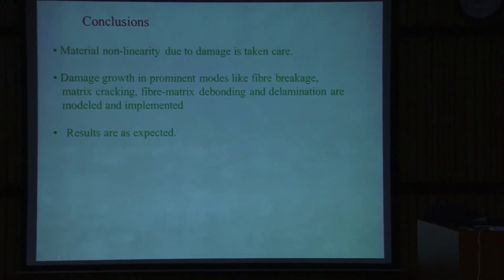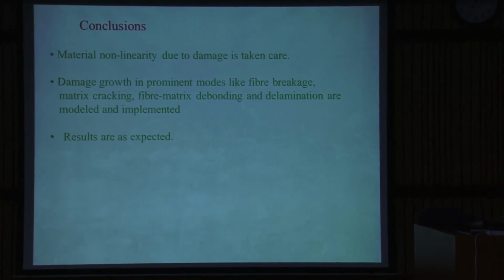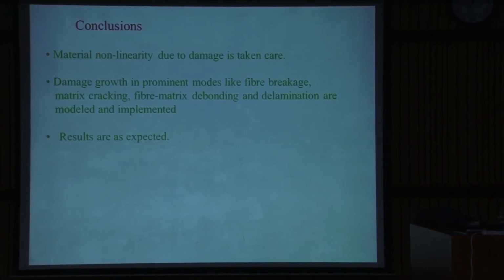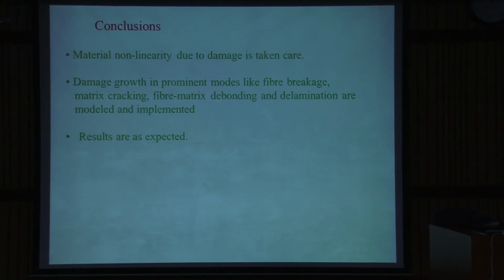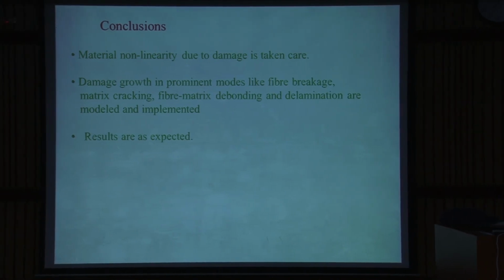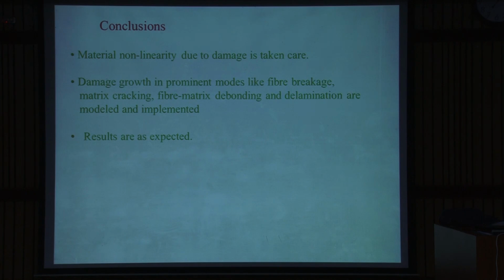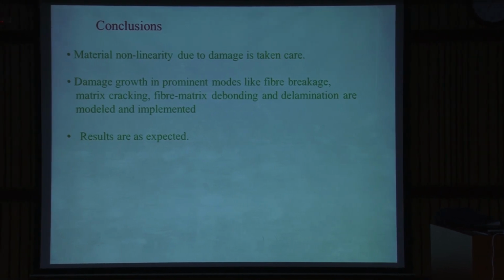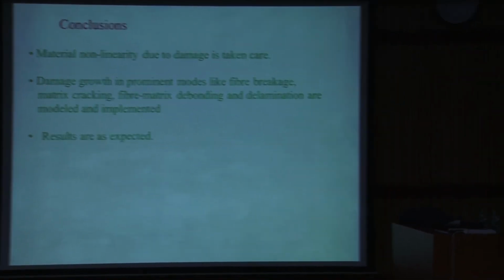Okay, so the conclusions are just qualitative. We have done this material non-linearity due to damage. Here the prominent modes like fiber breakage, matrix cracking, fiber matrix debonding and delaminations are modeled and implemented, and the results presented here are according to our expectations. In fact, we have some experimental verification as well, but I'm not supposed to disclose that. So that's why I have not given it.